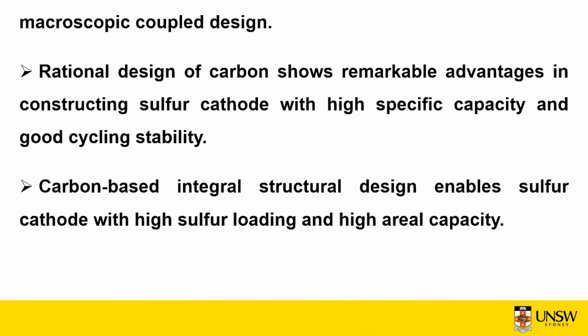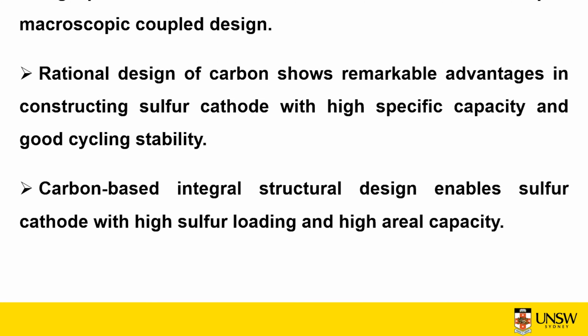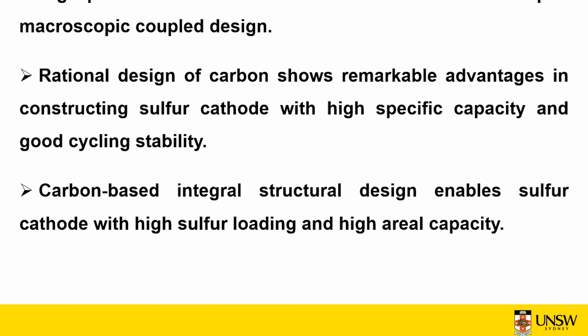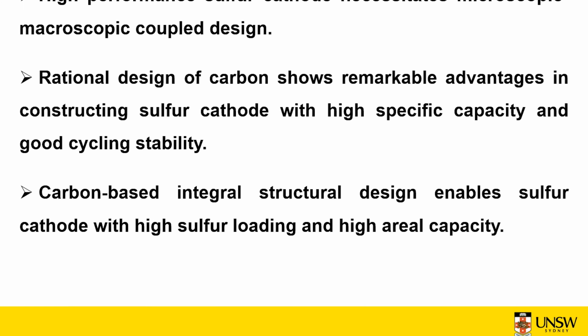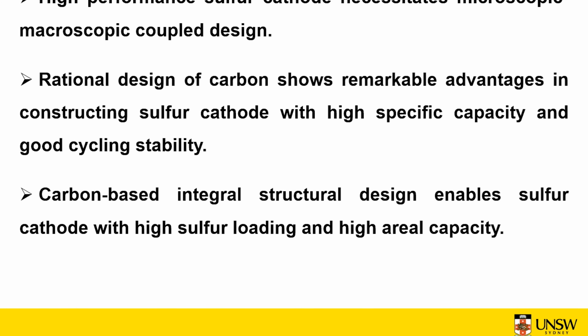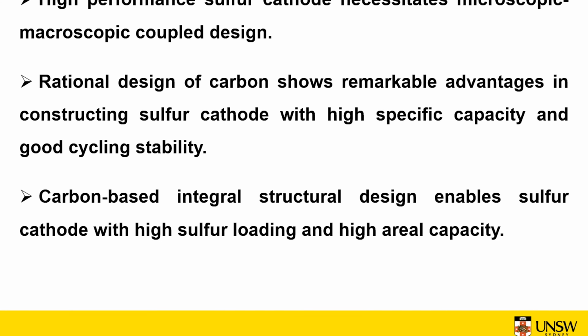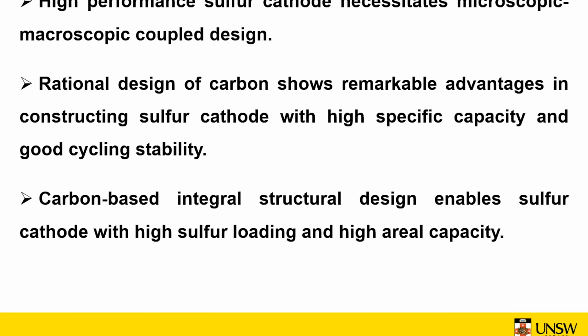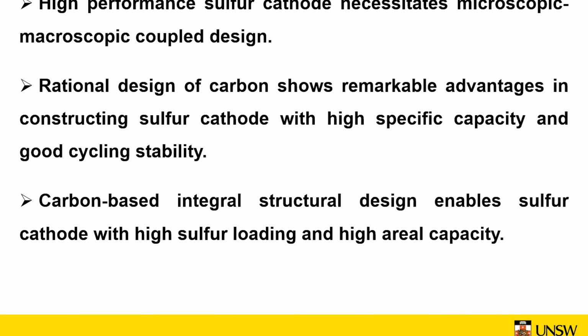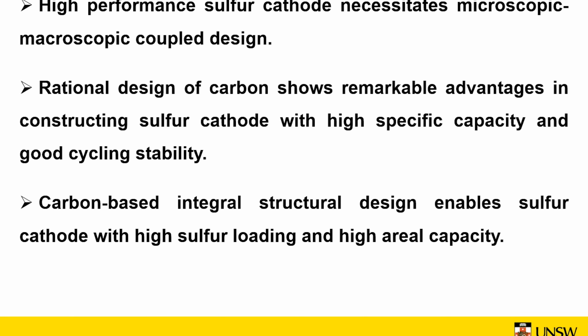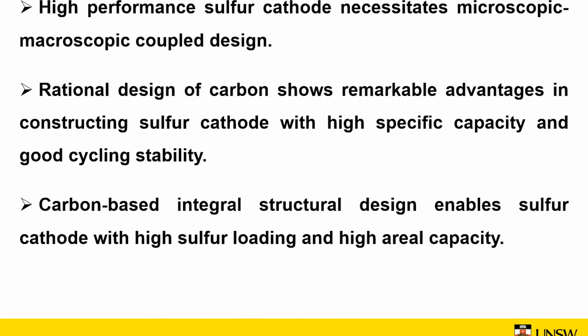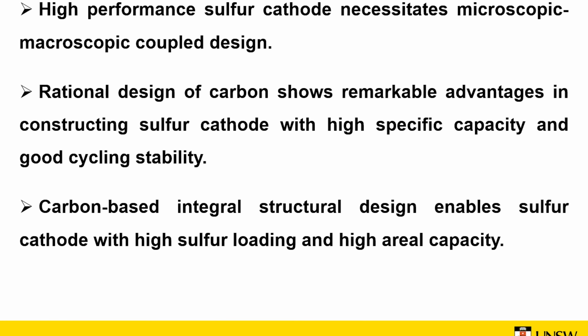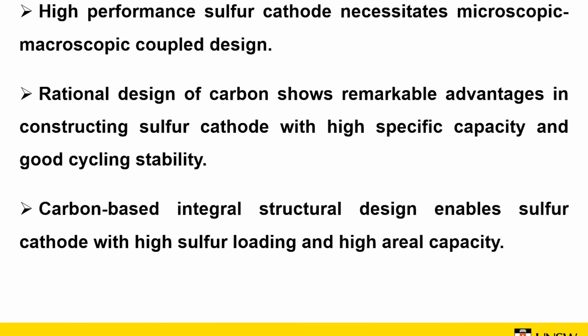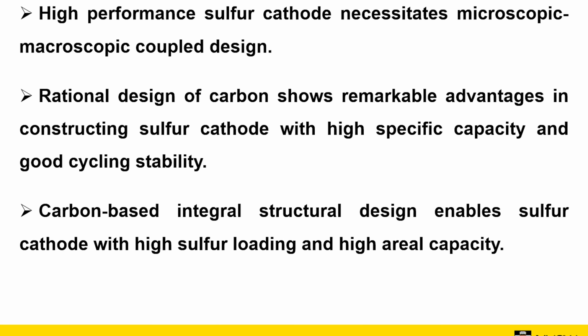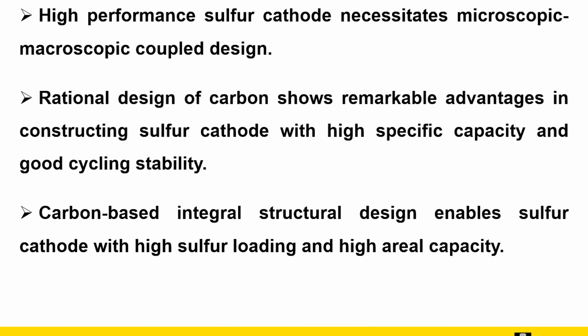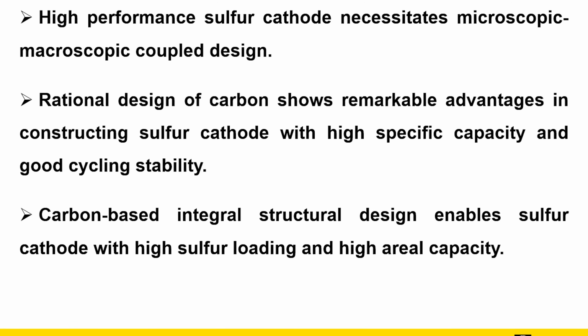To make a short conclusion, first, we propose that a high-performance sulfur cathode necessitates microscopic and macroscopic coupled design. The second is that the rational design of carbon shows remarkable advantages in constructing sulfur cathodes with high capacity and good cycling stability. And finally, carbon-based integral structural design can enable sulfur cathodes with high sulfur loading and also high areal capacity, which is very promising for practical applications.